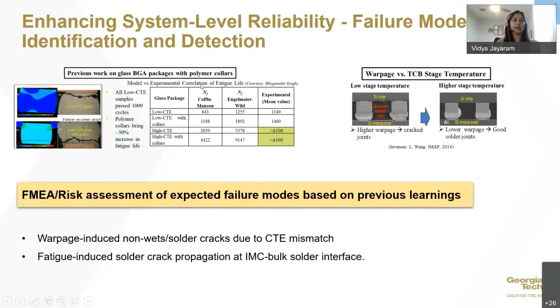One is fatigue related bump cracks, where, based on the prior work done at the lab itself, we saw failure at the BGA bump, closer to the substrate and bulk solder interface, for a low CTE glass, and we saw how that failure propagated to the lower end by using some sort of strain relief mechanism like a polymer collar. And this is less likely to fail compared to the one on the top. So that's how the board level reliability was extended. So that was one learning.